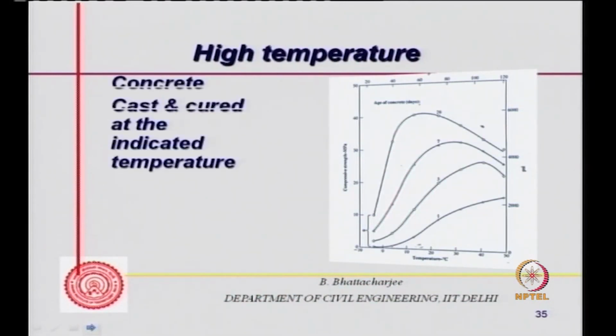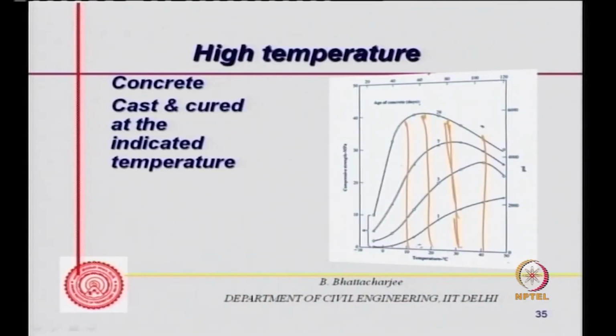What about temperature? Concrete cast and cured at the indicated temperature. Let us say this is temperature, 30 degrees centigrade, and this is age, 1 day, and this is 28 days. If you cure it at, let us say, 10 degrees centigrade, strength is here; 20 degrees, strength is here; 30 degrees, strength reduced; 40 degrees, strength reduced. So if you look at 28 days strength, curing at 40 degrees will give less strength than curing at somewhere around 20, 22, 23 degrees. Similarly, 3 days strength and so on.